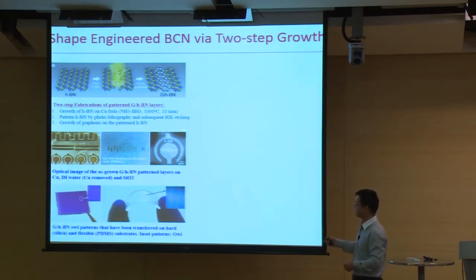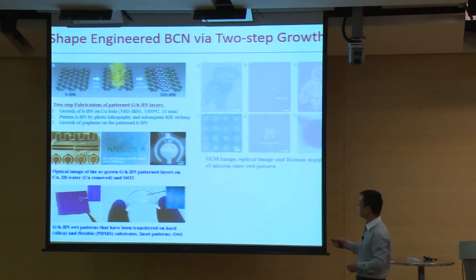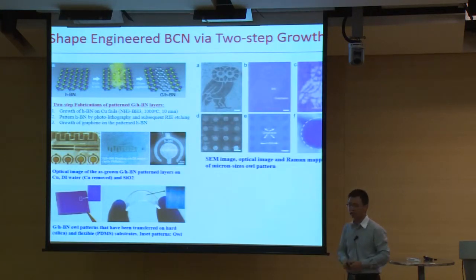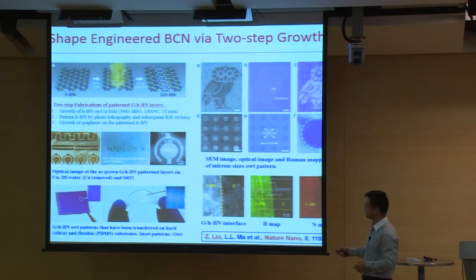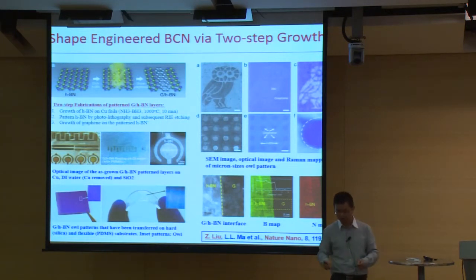And this film can be transferred to a rigid substrate like silica, and also a flexible substrate like PDMS. Because this method employs the photolithography process, we are able to make complicated patterns like this one, the logo of Rice. And we can also make circles, squares, triangles. And we examined the interface of these materials under microscopy. We can see this is a very sharp interface, but because of the contamination problem, we cannot get an atomic resolution image showing how they bond with each other.